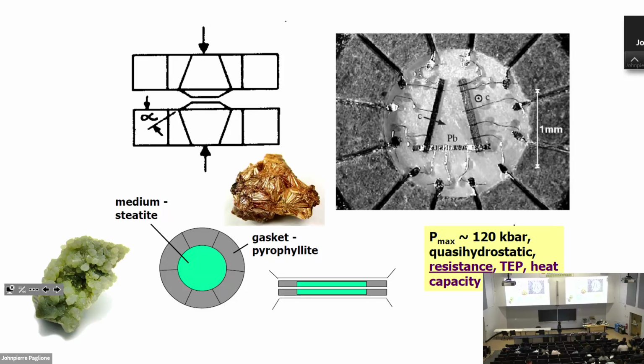And for this, of course, let's say you measure resistance. You need some electric contacts coming from your sample, going out of the gasket. So now you can't directly go to your cell. You have to go out of the gasket. So you drill some hole so that it can come out. Because of this, you cannot use liquid. You have to use some solid, otherwise the liquid is going to flow out of the hole.